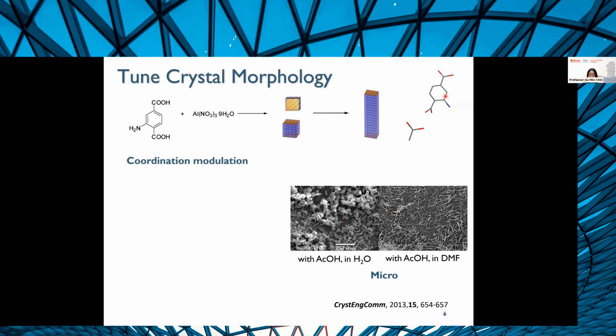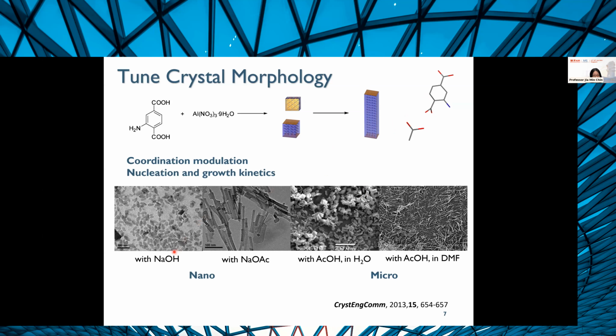And the reason for this, we speculated, was because this linker here actually exists in part in the zwitterionic form in water. And so it has this carboxylate deprotonated, and that is able to compete more effectively with the acetic acid. So this modulating ability of the acetic acid is limited. So you can also play with the nucleation rate of these crystals. Let's say you were to throw into the mix sodium hydroxide instead of acetic acid. In this case, this base deprotonates these linkers, and then you get very rapid nucleation and you end up with nanocrystals. However, if instead you use a base, but with the acetate in the mix, then you not only get really small nanocrystals, but they also happen to be rod-shaped.